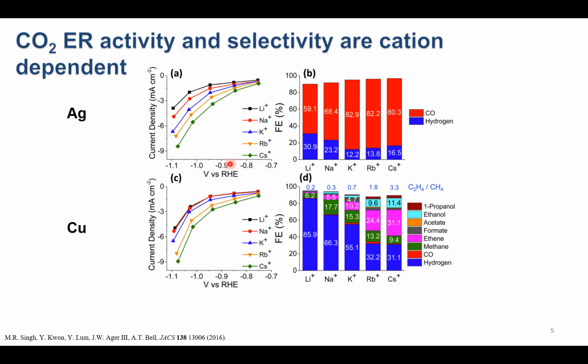If we look at just the bottom half of this figure here, this is showing CO2 electroreduction on copper. We can see that the rate of this reaction, given here as the current density, depends on the cation that is present in our electrolyte. Right? It's highest with cesium and lowest with lithium. Maybe even more excitingly, the selectivity is also significantly affected by the cation present in our electrolyte.